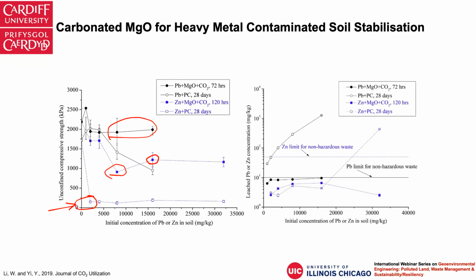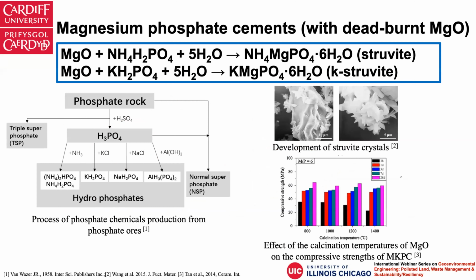Similarly, if you have no solidification or cement hydration at all, the zinc leachability would be extremely high. While for carbonated systems, the leachability of all of these heavy metals is below the regulatory limits. So this actually provides a method that can be used to both store the carbon dioxide in the ground as well as immobilize the heavy metals. But again, it is a solidification and stabilization combined method.